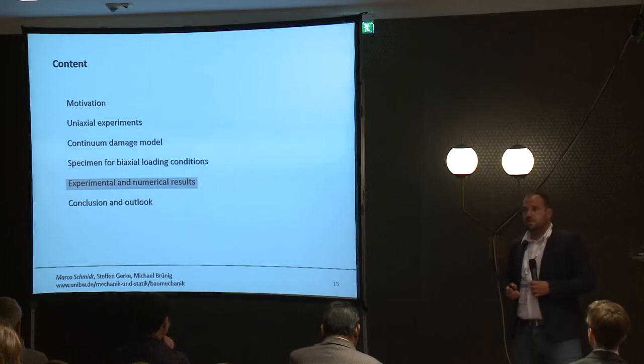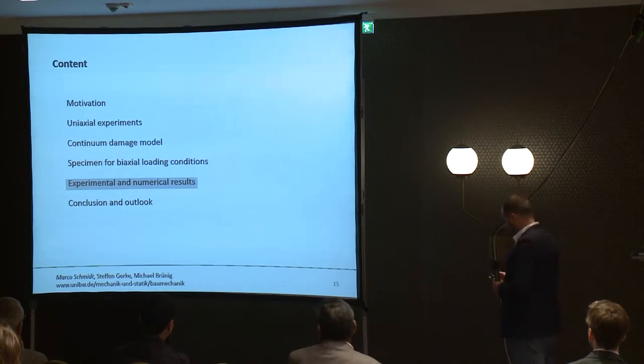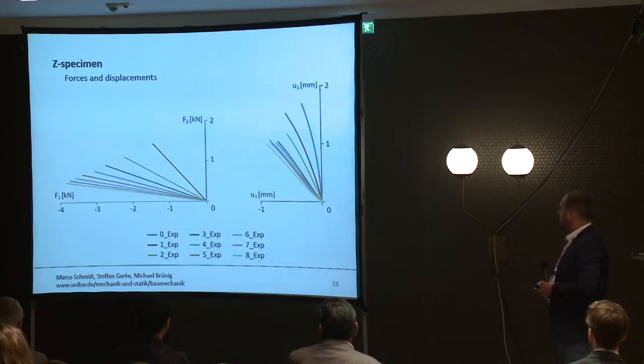Now, I want to show you the experimental and numerical results. For the numerical simulation, we used the finite element software Abaqus Mechanical, and we used solid elements for the mesh. We performed experiments with nine different load combinations. The load factor on the shear axis is always one and the load factor on the other axis varies from zero to minus eight to get negative stress triaxialities.